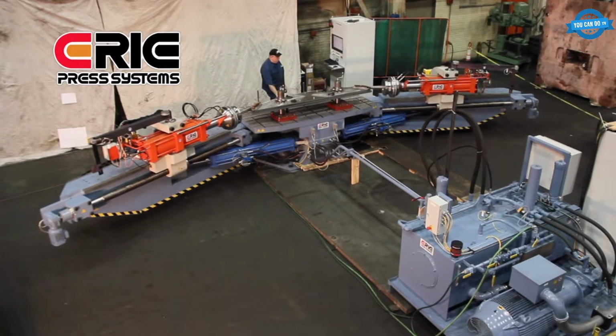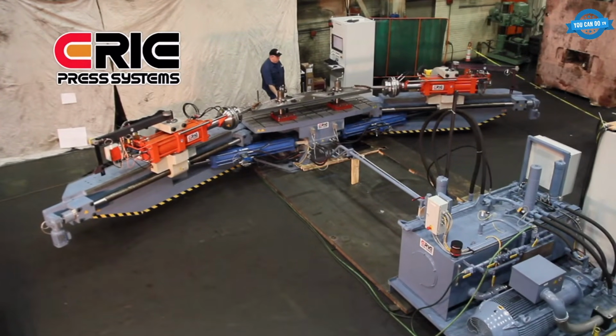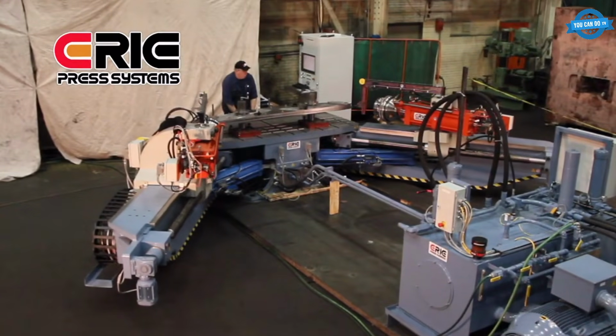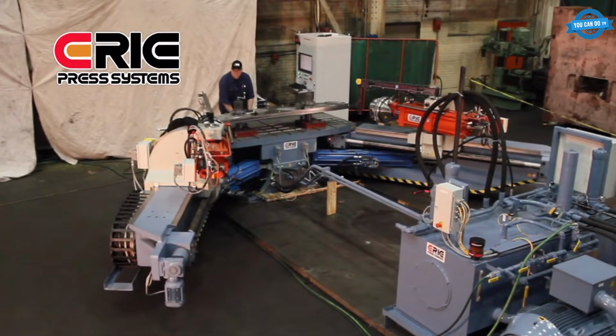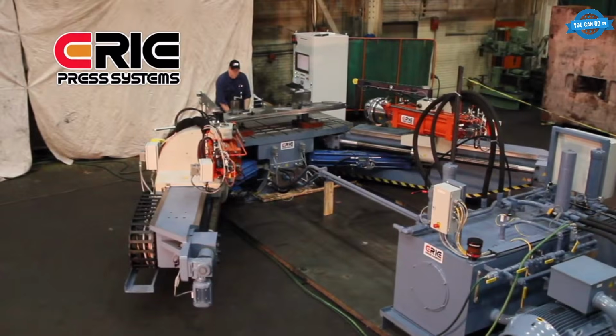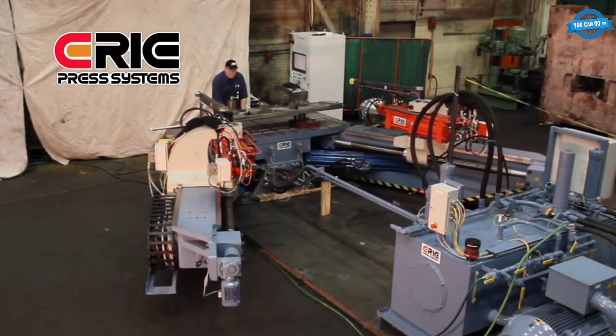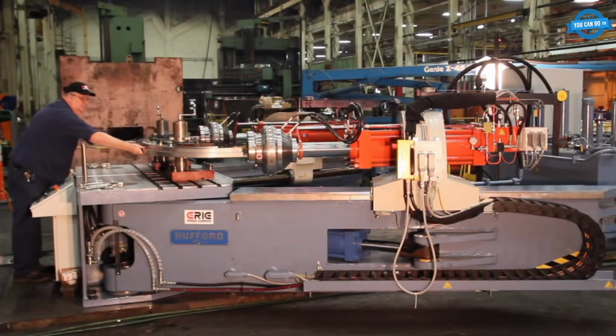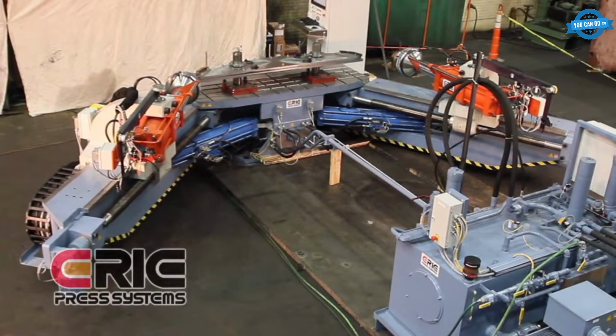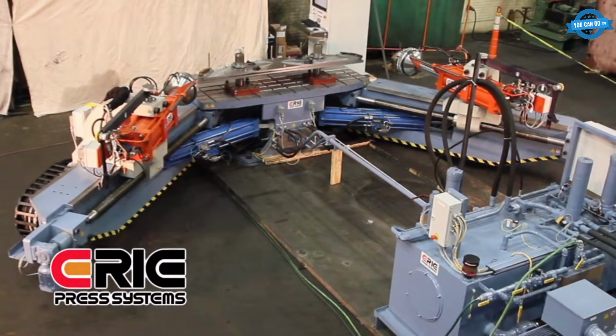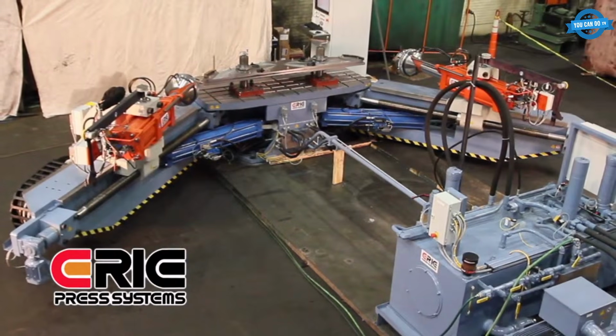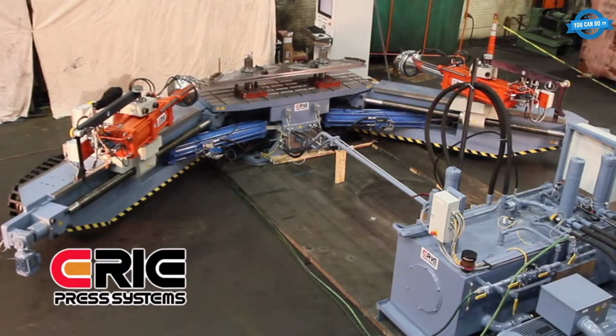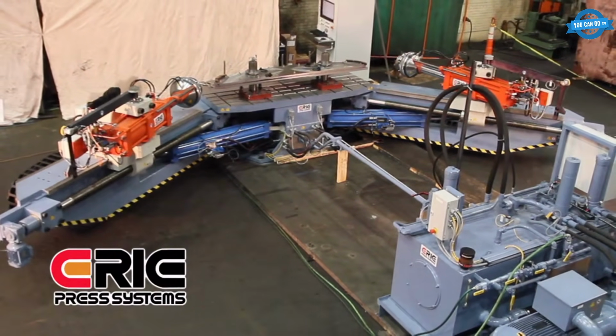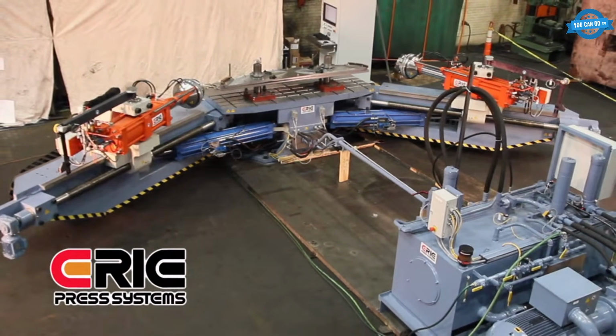Now take an extruded profile and add a twist. Literally, extrusion stretch forming grabs both ends of a straight metal profile, pulls it under tension until it passes the point where the metal would normally spring back, and then wraps it around a curved die. Because the metal is held past its elastic limit while it takes the new shape, it doesn't try to snap back. It stays curved. Better yet, the stretching actually increases the yield strength of the finished part.